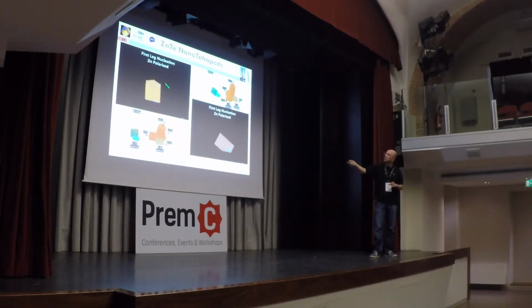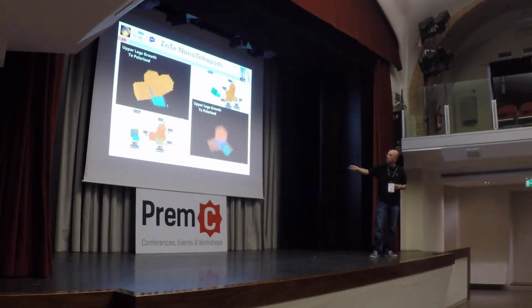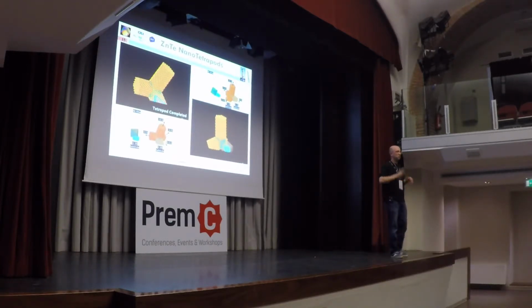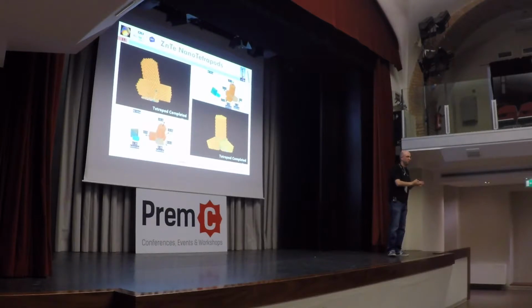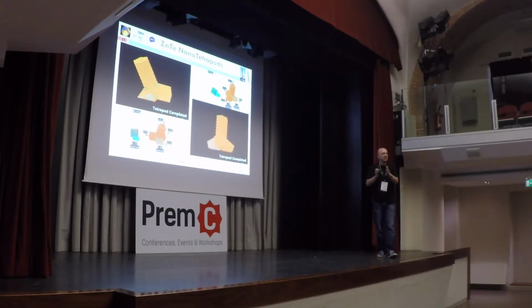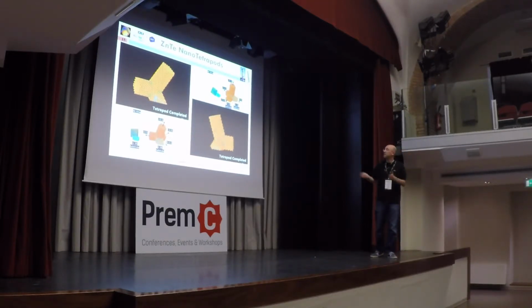We think about a second nucleation event here, creating a second octahedra, and then we will have 3 other possible anion-terminated surfaces for 3 other legs. So in this case, we end up with one tetrapod here with only one leg on top of the substrate, or with this other tetrapod with 2 different legs on top of the substrate. So just think about it. It's so easy. Just think about polarity. It's an easy rule, but you can understand all of these growth mechanisms.